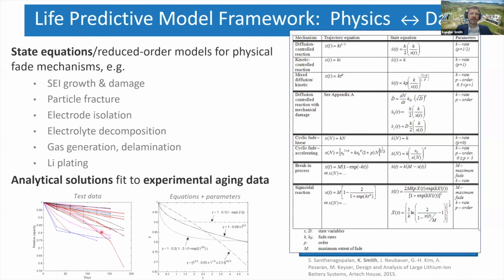Others that accelerate, like the red, we can fit with yet another model here. This accelerating cycling fade is this particular model. And this one says that if you take your state variable to be, say, negative electrode sites, the rate of negative electrode site loss with each new cycle is inversely proportional to the amount of remaining negative electrode sites. And so as you have fewer and fewer negative electrode sites, that's going to accelerate your fade rate.